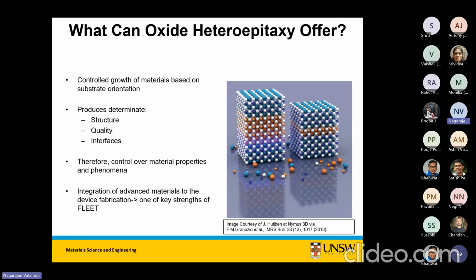But the student is obviously smarter than me, because he said, why do you need bismuth ferrite? Look, I can get you iron oxide at scales and sizes and shapes that nobody else can get. And the fact is, we can exploit bismuth's volatility. If you don't know, bismuth has a very high vapor pressure. It's like lead. If you don't control the chamber pressure, you will lose bismuth, right? Now, the rest of the world is obsessed with controlling that evaporation or sublimation of bismuth. They don't want bismuth to leave.